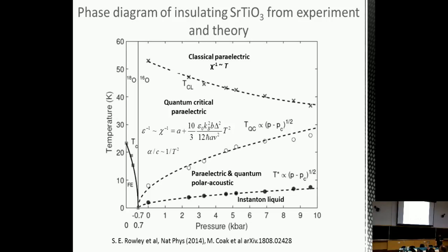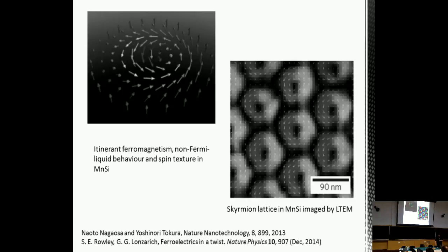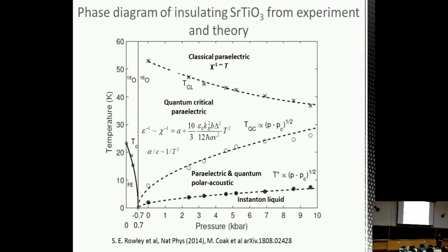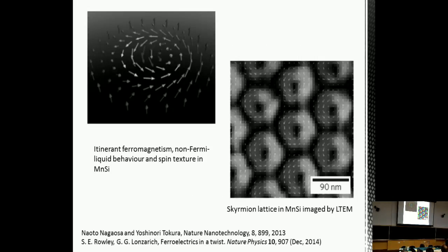And from measurements of thermal expansion, thermal conductivity, and piezoelectric resonating ultrasound spectroscopy, it's possible that in this part of the phase diagram, on the paraelectric side close to the quantum critical point, we could have some type of polarization textures, which are slow-moving modes. Here I've shown the case in itinerant ferromagnetic systems where vortices and skyrmions can form close to the quantum phase transition. We believe that these could also form as polarization vortices close to a ferroelectric quantum phase transition.